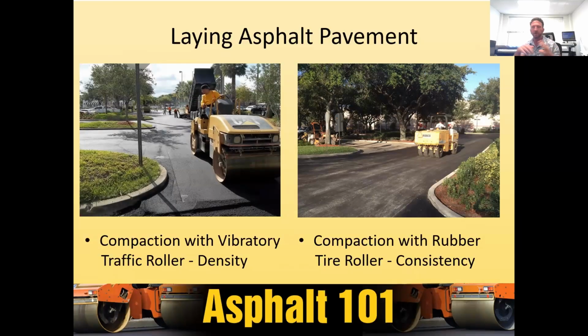This all has to happen in a span of about an hour to 2 hours to ensure that I'm compacting that material at a temperature of about 225 F or above. If I don't compact it at that heat, if I let it get a little bit colder, then I risk loose aggregate at the top called raveling. I risk segregation, where you can see some voids in the aggregate themselves when you look closely at the pavement surface. The ideal pavement surface is going to look very, very flat, like glass.